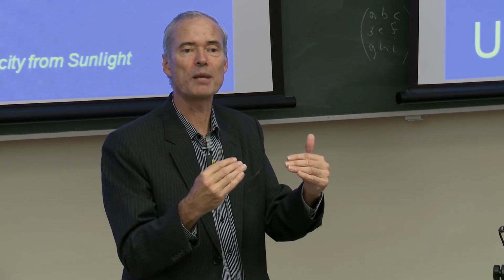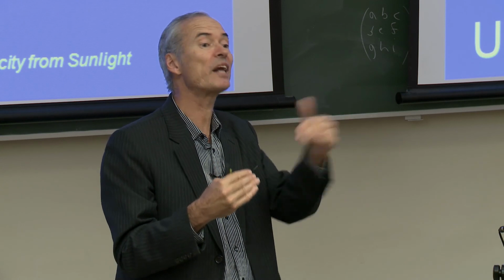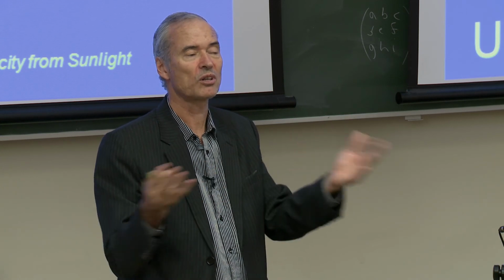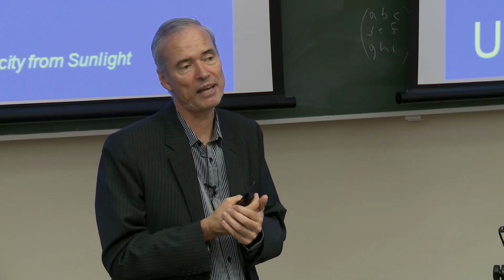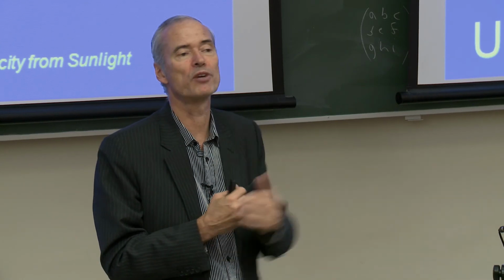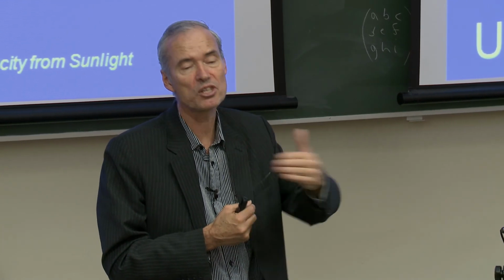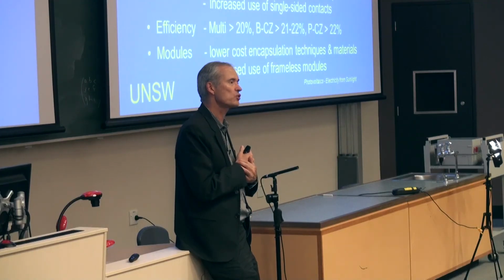And now we're seeing the predictions are no longer limited to 20%, they're now up to 21 to 22%. Because quite a few companies are getting to the 20% now, or will be very soon in large-scale manufacturing. And there's still more room for improvement, and so we're going to keep seeing these improvements take place. 21 to 22, I think, is almost certainly achievable. And we believe that 23% is achievable with the standard P-type commercial Czochralski wafers that most manufacturers are using. So that's where it's all heading.